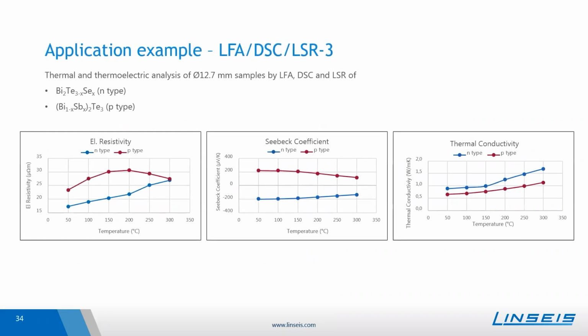Analysis with different instruments was performed on N-type and P-type bismuth telluride samples, differently doped. The electrical resistivity and conductivity, as well as the Seebeck coefficient, were measured with the LSR system. The LFA determined the thermal diffusivity, the DSC the specific heat capacity. The combination of both led then to the thermal conductivity. Here in this example, you can clearly see that the N-type and the P-type material show completely different values and also different behavior with temperature.